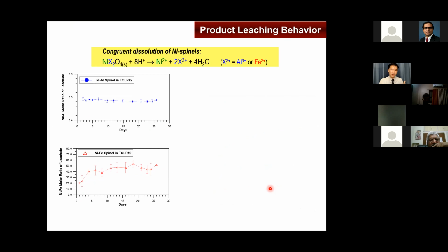So we start to go through the different concentrations of them. And we find out, again, if it's a congruent dissolution, one nickel comes out, you should have two trivalent cations coming out, and the ratio of these divalent and trivalent should be 0.5. And that's exactly the same for the nickel aluminum spinel. But for nickel ferric spinel, it's not the case. The ratio is very, very far off.